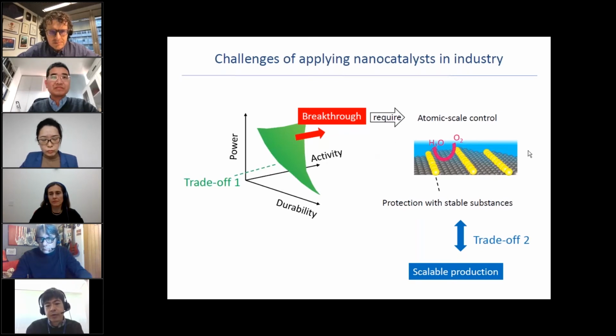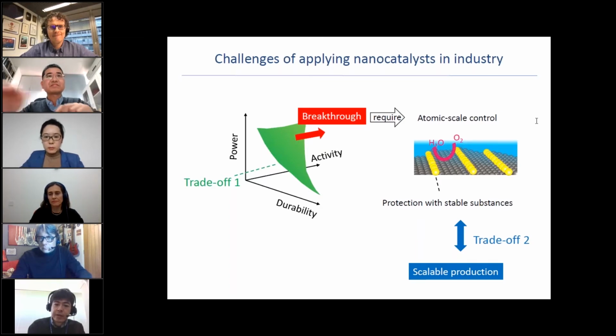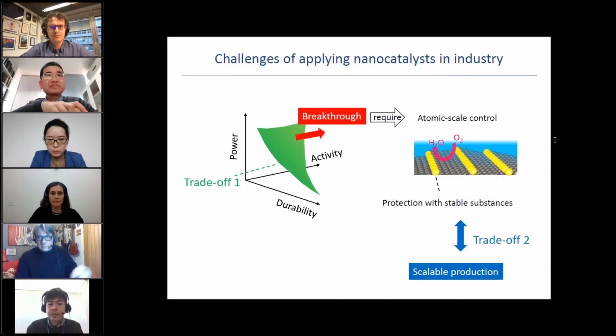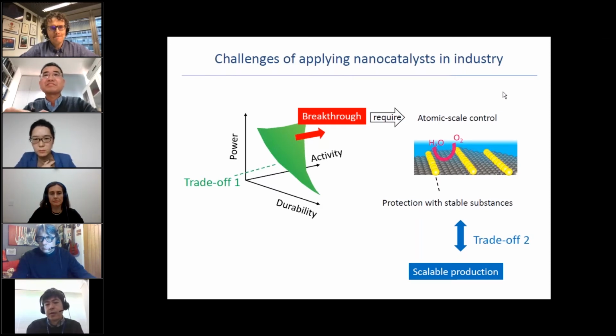But controlling the surface structure at atomic scale poses another issue of mass production, probably between the precise control of nanostructure and the cost of production. And this is a problem because if we cannot find a scalable synthesizing method, engineers in the field may regard the concept as useless. This can happen sometimes because in the production phase, there may not be sufficient time for developing a new synthesizing method for a state-of-the-art catalyst.